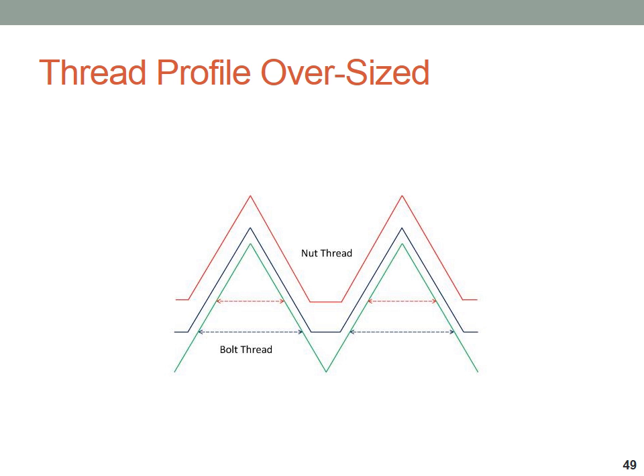And in the case of something like mechanical galvanizing, where we are coating both the bolt thread and the nut thread, it actually has an 8-to-1 multiplier. So what starts out as a relatively thin coating, we have to multiply that thickness times 8 in order to come up with its effect on thread fit, and that can be significant. If you've got a notebook in front of you, many of our coatings are approximately the thickness of a sheet of paper.